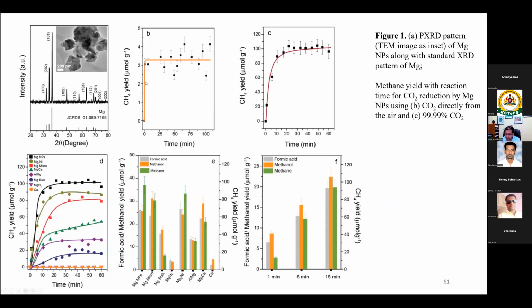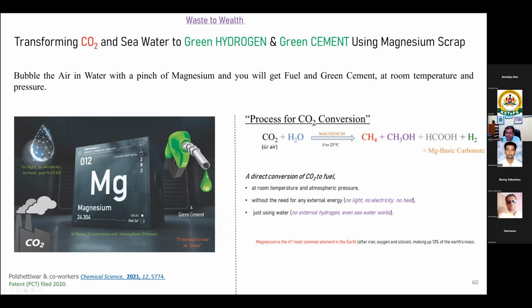If I take air, well, by the way, you don't need pure CO2. Even if you bubble the air around you through a glass of water with magnesium powder, you still get these chemicals because air has 400 ppm CO2, and this reaction is so fast at room temperature that even the CO2 in the air gets converted.